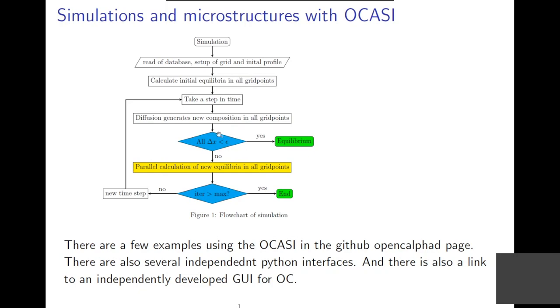And if the change in the composition in all the grid points is zero, then you have reached the equilibrium state for the whole material. Otherwise, you can do a new calculation and obtain new equilibria in all the grid points, and that gives you chemical potential, and the chemical potential will drive your diffusion, and you take a new time step, and you go on like this until you have the number of time steps you are interested in.